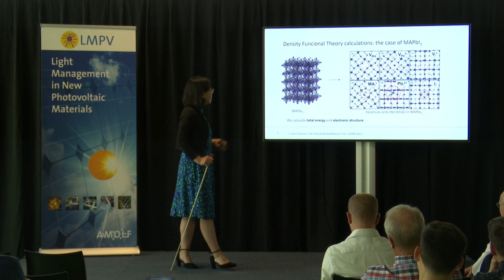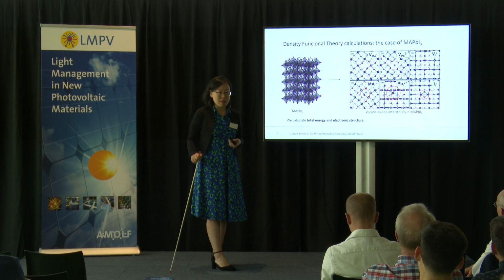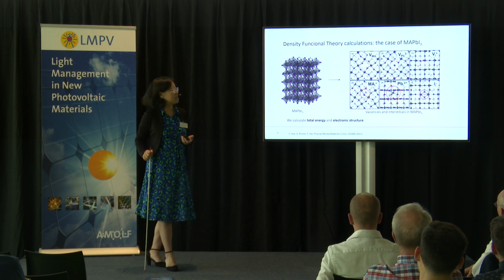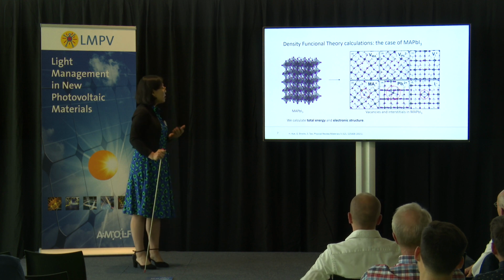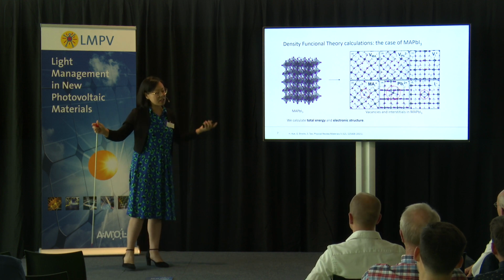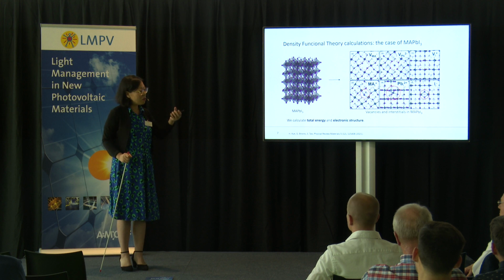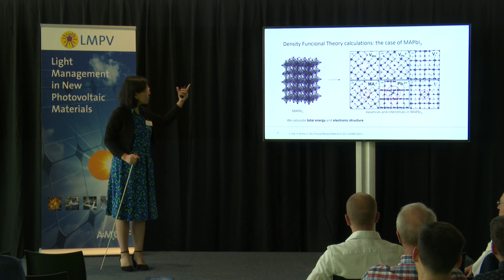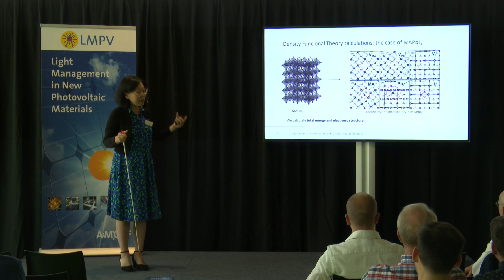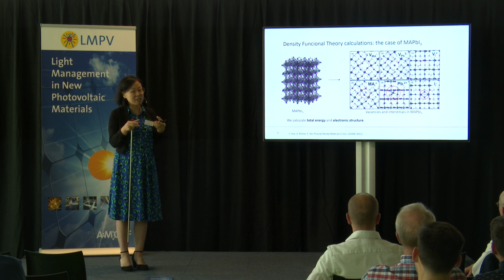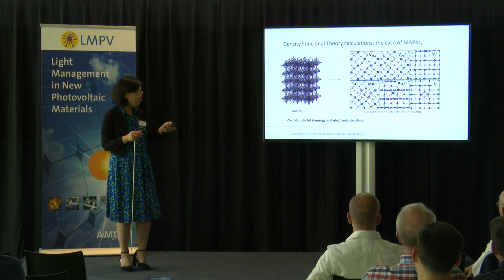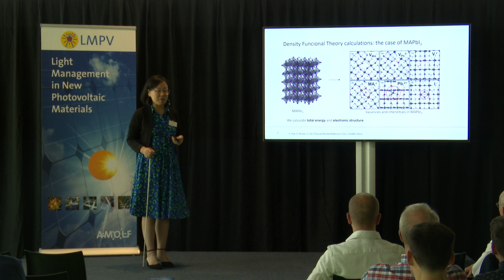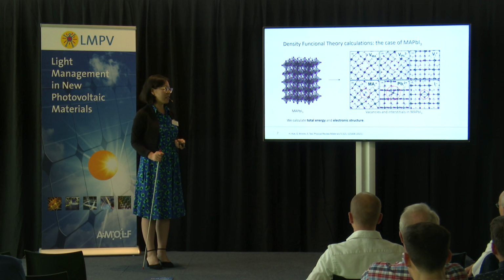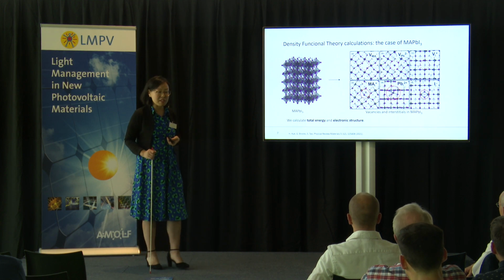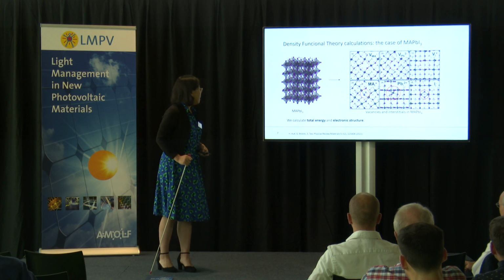To do that, we use DFT calculations. Many of you know a little bit what DFT is. What we do is we create a large enough cell, and we make all kinds of defects. You can see there are different pairs of defects. And we make sure that we systematically look at them, the system is charge neutral, and we calculate the total energy of the pure, perfect and the defective lattice. And we also obtain the electronic structures.